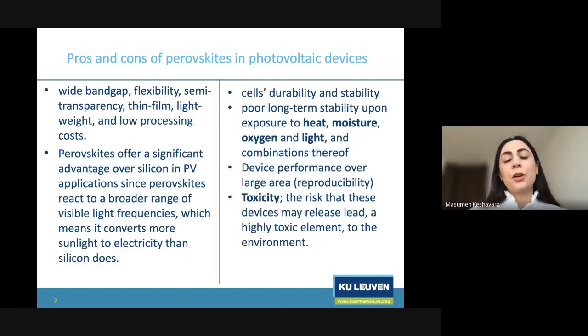But there are some drawbacks, and there is always some drawbacks. So the most important one, to my opinion, is their stability. They have poor long-term stability upon exposure to heat, moisture, oxygen, and light. And even light, for example, the combination of these can increase their degradation paths. For example, light can actually promote the degradation paths from the defects and so on into the system.